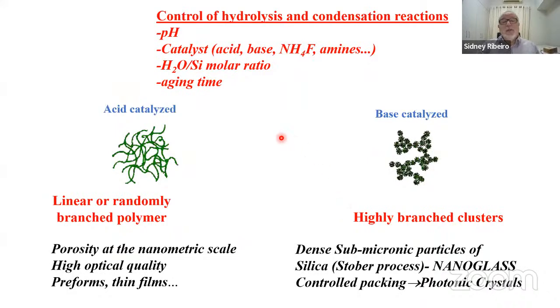By controlling the reaction conditions, the hydrolysis and condensation reactions, and we can play with the pH, the catalyst, the water to silicon molar ratio, for example, the aging time, we can obtain completely different materials. In general, if we use acid-catalyzed processes, we will have linear or randomly branched polymers. Macroscopically, this will present porosity at the nanometric scale. So they present in general high optical quality. They are transparent, so we can make preforms or thin films.